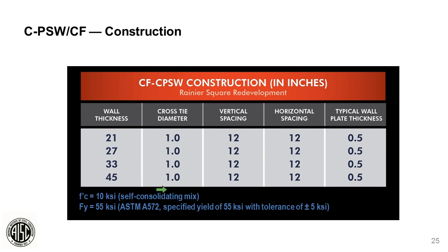If we talk about the parts and pieces of the system, we're going to dig into that a little bit here with the next few slides. The composite plate shear wall construction was comprised of essentially two elements. There are outer face plates or side plates of various thickness. In this case, all of the wall thicknesses were nominally a half-inch thick steel plate on each face. That comprised about 75 to 80% of the entire core.